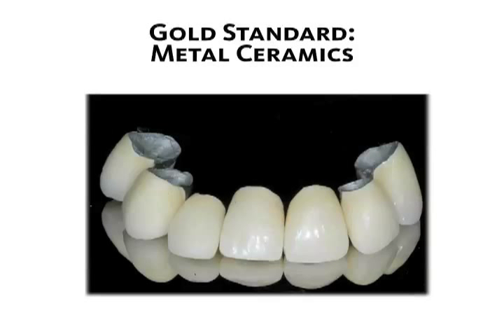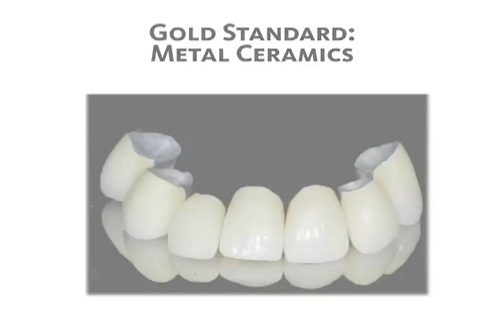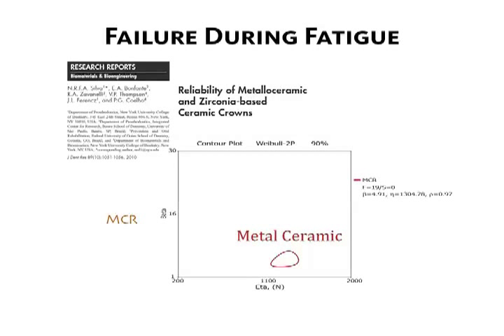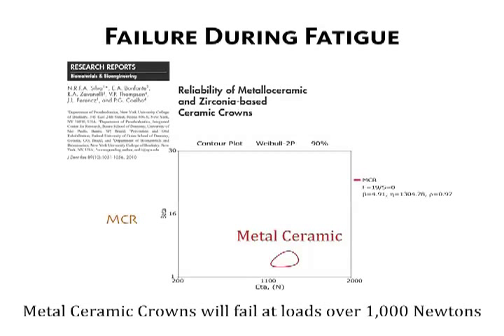When we look back in time, we must acknowledge that metal ceramic restorations are the gold standard, and for this reason, we will look at published data addressing its mechanical behavior so we can compare it to other materials. This graph shows that under fatigue loading that simulates mastication, metal ceramic crowns will fail under loads above 1,000 newtons, which is way beyond the physiological chewing forces. Therefore, any new material to be used for an implant-supported reconstruction is expected to fail in the same load range or higher than metal ceramic.